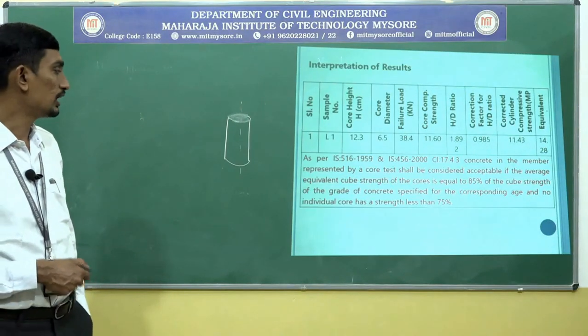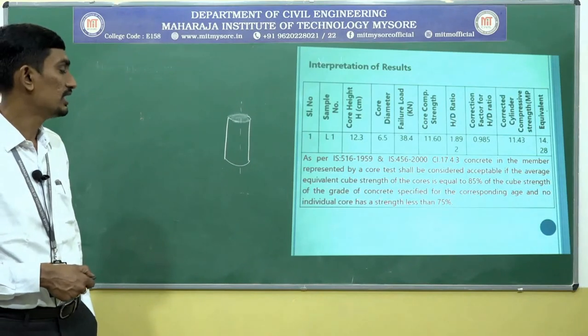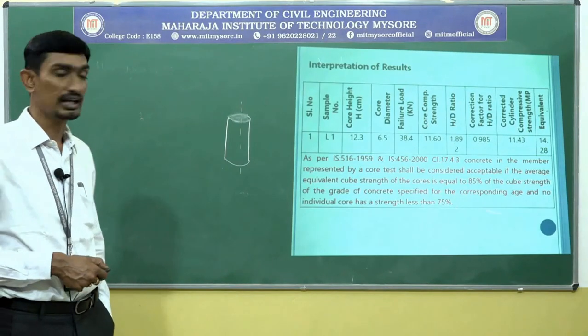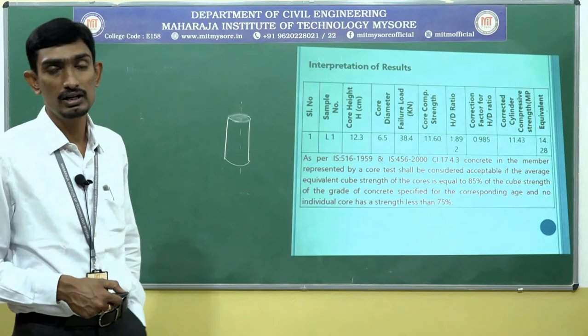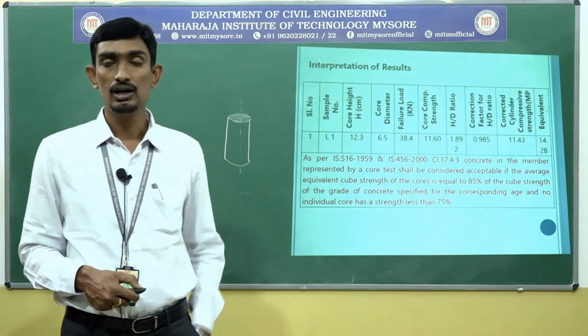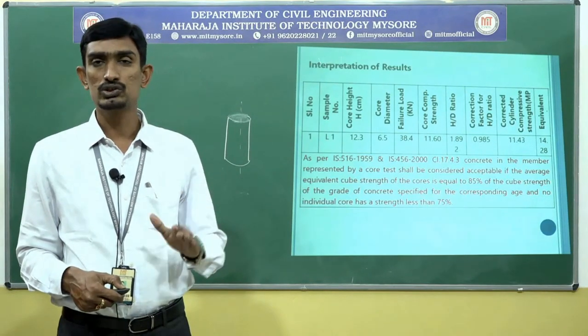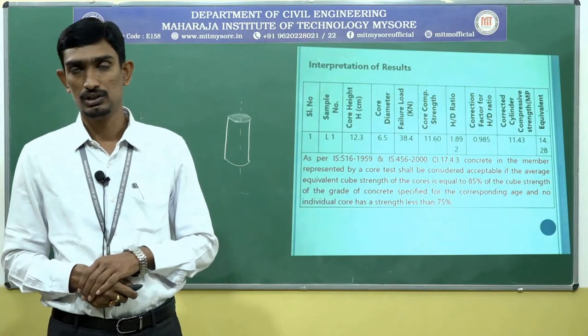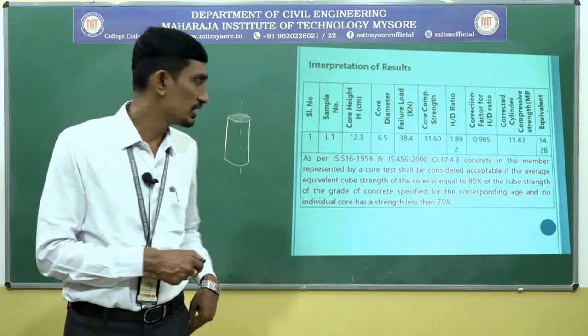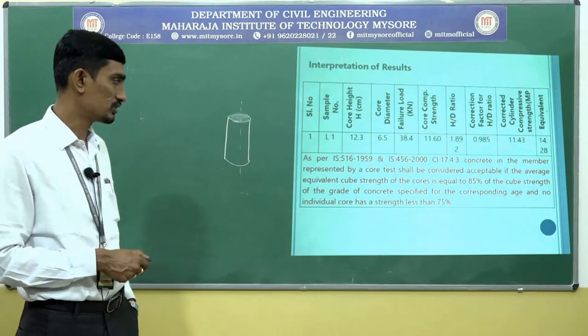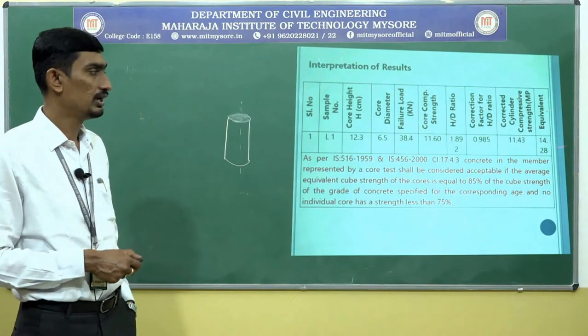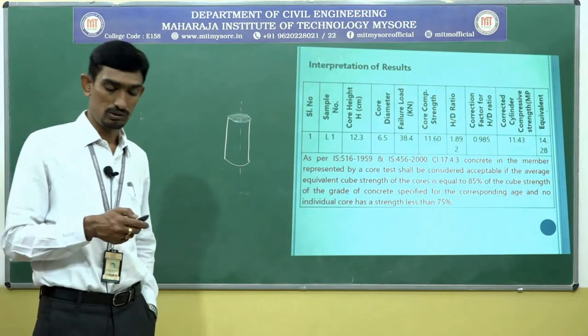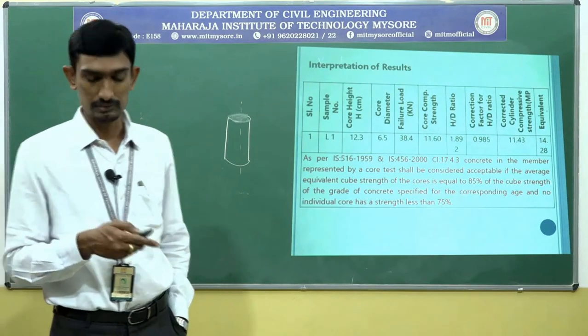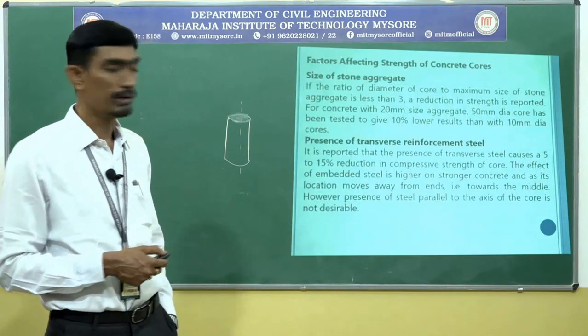And one more thing, no individual core should have a strength lesser than 75% of the grade. That means whatever the grade of concrete provided, each individual core should not be below 75%. So this is the provision given by IS 456. If the testing results abide by these two conditions, then we can go ahead with the core sampling. Did you get my point?